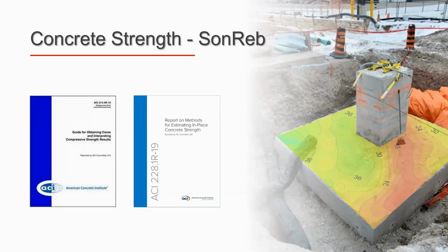So this will save time when you have to perform remedial work or where you are forced to remove poor quality areas. Again, in a very similar setting, we did a very interesting project on a large scale concrete slab, which was exposed to extremely cold temperatures after cast. And the contractor had to prove that the concrete had reached the strength. So we were hired and we performed the same philosophy. We performed both tests and used the simulations to come up with the contour map of concrete strength. And it helped them show the areas that are potentially problematic and substandard in terms of concrete strength.